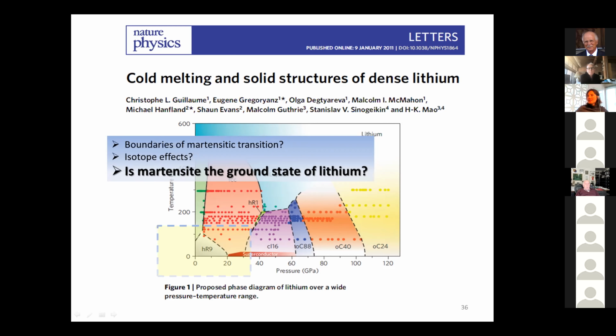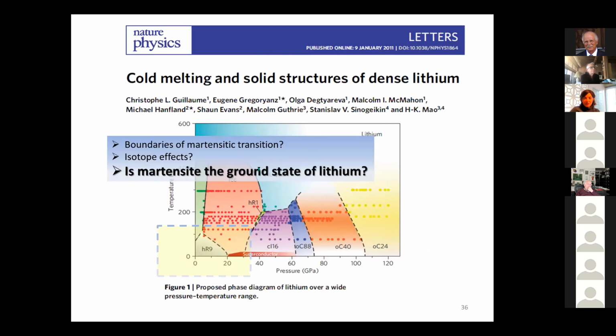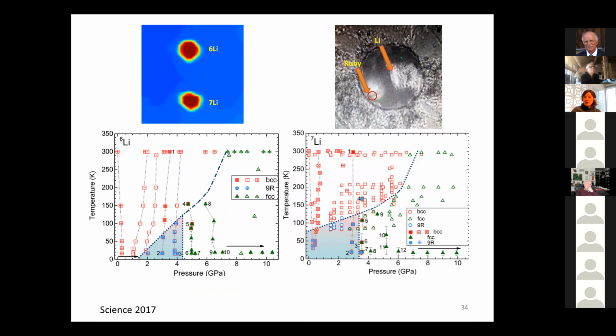So what we did is that we used a pressure medium, number one, for all of our studies pretty much. We used helium as the pressure medium. In a picture that I showed here, I didn't go through the pictures because I thought it was going to be too dense, you can see, for example, the lithium that is embedded inside of the helium pressure medium. So that's one thing.